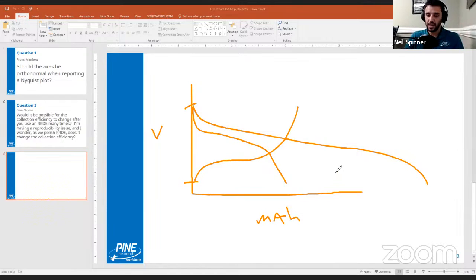takes energy. And then once the SEI is formed, mainly on the anode, a little bit on the cathode too, once it's formed, the battery settles into this normal charge discharge kind of behavior, if it's a good battery, right? Of course, if it's not behaving well, that's a different story. But if it's a well-made battery, it settles into this normal charge discharge behavior. But the SEI is a decomposition layer that forms on the, it's a weird phenomenon as I understand it.